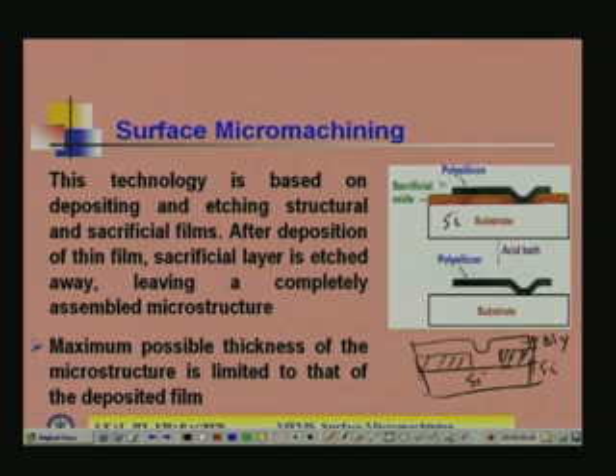So, that means it will etch from the top also, and after completely etching this particular location here and here, it will etch in this direction, it will go here, it will go here like that. So, wherever the oxide is completely removed, what will be there? It will be completely hanging. Because it is isotropic etching, it will go laterally, and the selective etching you are using, buffered hydrofluoric acid, will not etch the underlying silicon. So, it will go in this direction, and again in this direction, and on the other side also, like that. In this way the complete oxide will be removed, and this structure will hang. So, that is basically surface micromachining.